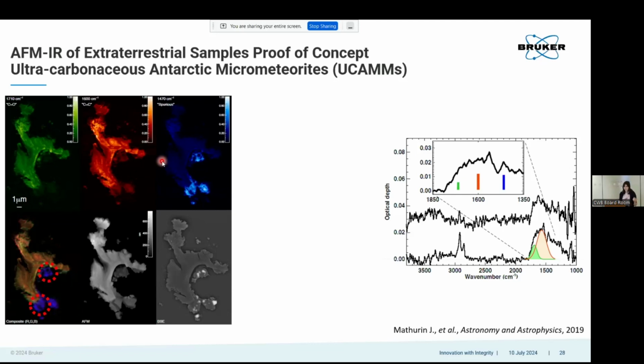From this, we can see the micrometeorite here in an SEM, and here in the AFM itself. You can see that it's actually quite flat. This is an important part of studying these materials: you want them to be as homogeneous as possible. There are a few different ways to do this. In this case, they take two pieces of diamond, a very, very hard material, and physically squish the micrometeorite between them to get it to a defined thickness. That is very important because AFM is so sensitive, you want your material to be as flat as possible. When we take spectra over it, you start to see variations in the spectra from location to location, and we can map that out.